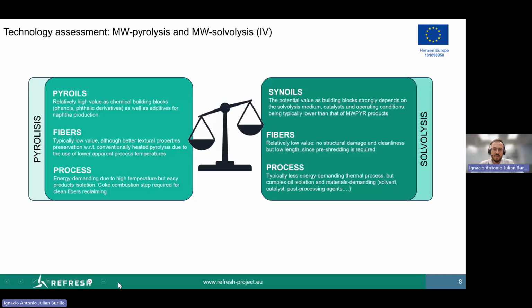Regarding solvolysis, the potential value as building blocks for the oils strongly depends on the medium, catalyst and operating conditions, being typically lower than that of the products obtained under microwave-assisted pyrolysis. The fibers have relatively low value with no structural damage and cleanliness, but the length of the fiber is rather low because we need to pre-shred them to be fit on their stirred tank reactor type.